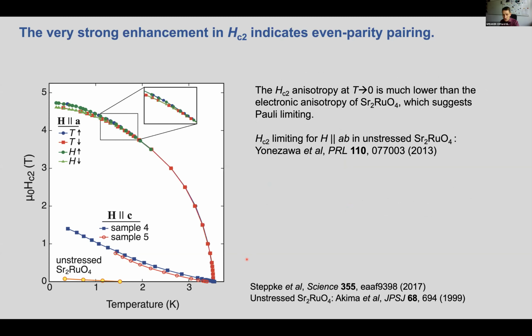Similarly, if we look at the in-plane Hc2, that also gives strong evidence for even parity pairing. So the in-plane Hc2 saturates at a little bit more than 4.5 Tesla at low temperature. Now this ratio, 4.5 Tesla to 1.5 Tesla, is much smaller than the intrinsic band electronic anisotropy of strontium ruthenate. To get an idea of the orbital electronic anisotropy, we look at the slopes here, dHc2/dT as we approach Tc. And the in-plane Hc2 comes in almost vertically. So that says that the underlying electronic anisotropy is very strong. The orbital limited in-plane Hc2 should be many tens of Tesla.